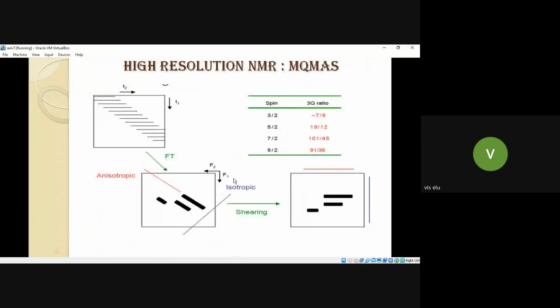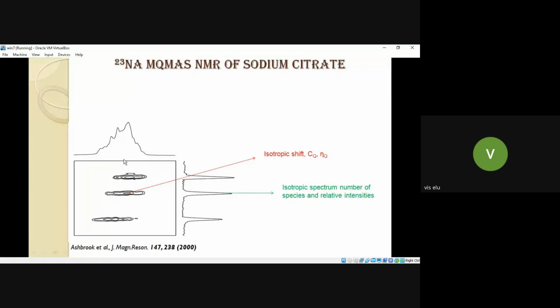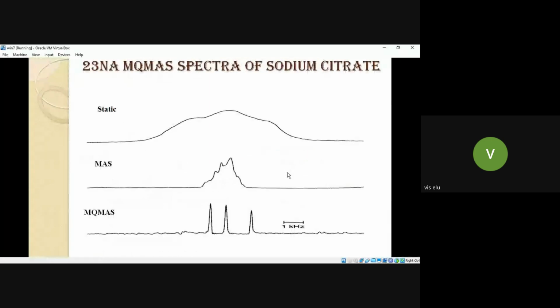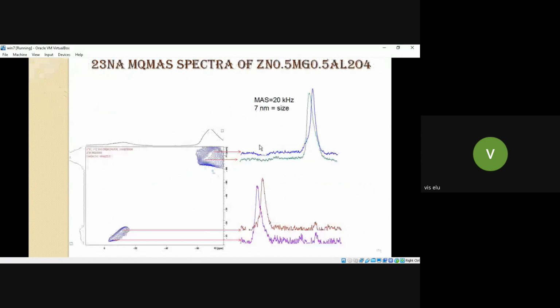I'll move on. I'll show you some 2D spectra so that you will understand them. As I told you, a broad spectrum will be there. This is what I did in sodium citrate, and you see well-distinguished contours. From here you can fit the contour and get this CQ, eta Q, and the isotropic chemical shift. Only MQMAS can resolve the spectrum. Magic angle spinning will not resolve the spectrum. This is a static one. This is one sample I did, and you can see that the spectrum is completely resolved in one dimension.